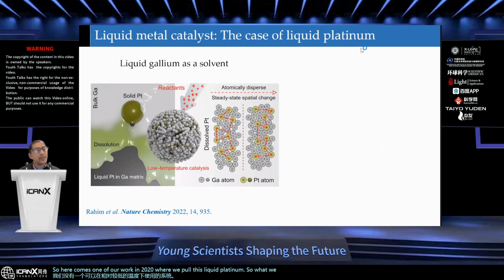What we did is pretty straightforward. Have solid platinum with a known amount, dissolve it in liquid gallium, but the solubility limit is really, really low, though they still dissolve quite a lot. But I must say that it is low, meaning that it goes to 0.001 atomic percent. But since we didn't know the highest level of a single atom's catalytic activity, maybe that is enough. And that is how I perceived this work. It was a really, really fascinating journey. This work was for me.